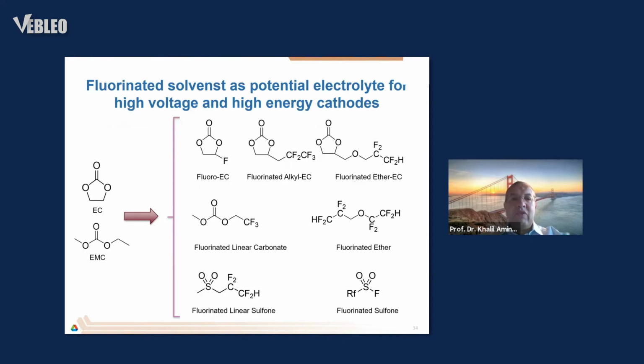At Argonne, we have looked at fluorinated solvent. This is a mistake here, sorry. As a potential electrolyte for high voltage. You can see we looked at a whole bunch of different fluorinated solvents, either fluoro-EC or fluoroalkyl EC, or fluorinated linear carbonates and ethers. We looked also at sulfones and fluorinated linear sulfones, and a combination. The first thing we did is we applied the DFT calculation to look at the potential stability of this electrolyte.